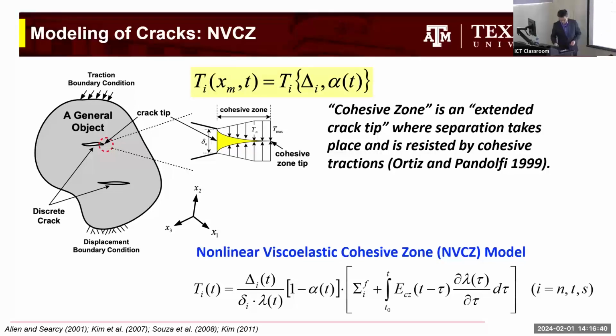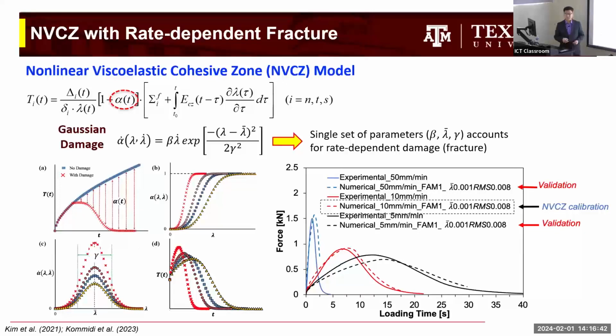In particular, regarding the alpha, alpha is an important part because alpha is actually simulating how damage progresses. And we know materials like asphalt or bituminous material, the fracture is rate dependent. It's a viscoelastic fracture. So we try to represent it better by using this Gaussian damage evolution function. That is very nice, by having these three, a single set of parameters, account for the rate dependent fracture quite efficiently. So it's a really good efficiency.